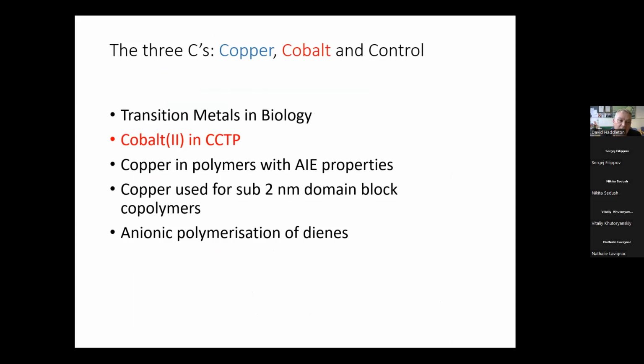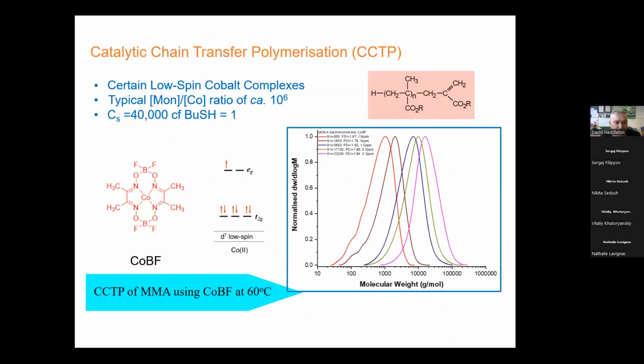So having looked at that, how do we use these transition metals in polymer chemistry, and why would we want to use them in the first place? Cobalt 2 in catalytic chain transfer polymerization. The catalyst we're going to use is this. It's called cobaloxime, and if you remember the structure of vitamin B12, it's quite similar. We've got cobalt 2 as drawn, in square planar geometry with these 4 nitrogen ligands. It's got this strange boron difluoride, but that's there to make it into a heterocycle, to make it acid stable.